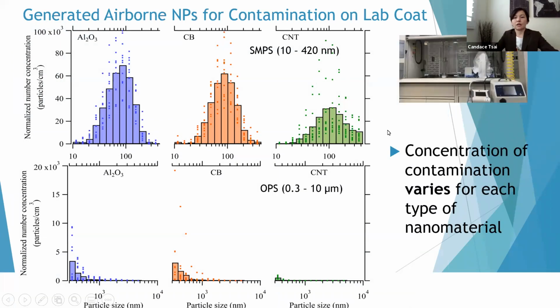Okay, so this is the data regarding the contamination. We aerosolized those three different nanoparticles, and we found the level of contamination from the aerosol concentration are different because that's the nature of the different types of nanoparticle. We found it's much easier to aerosolize aluminum oxide particles, and the second easiest is carbon black. Carbon nanotube is much harder to aerosolize into a very high concentration in the small size range.